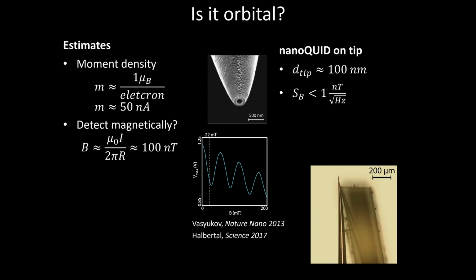And you can do the rough calculation and say the fringe magnetic fields you're going to be able to see if you just try to look at it are 100 nanotesla, 10 nanotesla. They're really quite small. So to do this, it's part of what we built this type of instrument for. We use these nanoSQUIDs on tip. They're tiny little SQUIDs you can make on the tip of a quartz tube. They have a strong magnetic response. Actually, they work up to quite large magnetic fields because all of the dimensions are so small. Very recently, we've been able to improve these by another order of magnitude. So we now have magnetic field sensitivities in the picotesla per root Hertz regime, which is really very small fields. It makes it possible to detect a single spin inside your SQUID loop in a few tens of milliseconds.